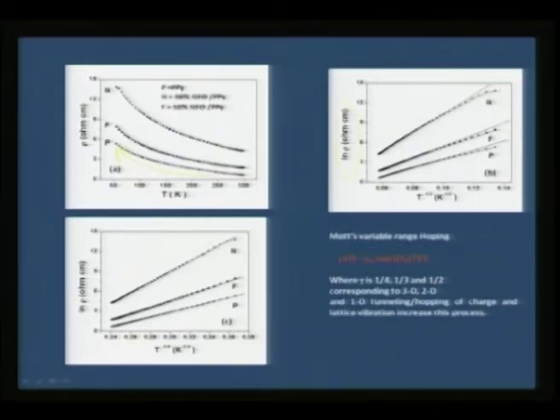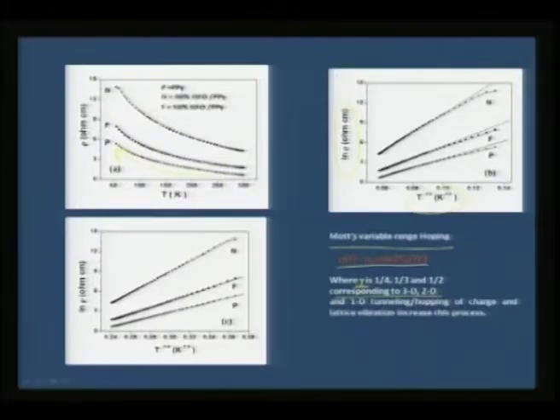Therefore, if you plot log rho versus T to the power minus half, this is typically a model related to Mott's variable range hopping. If you make a plot of this, you can see that there is almost a good agreement over the entire range for these particles, indicating that there is a 3D variable range hopping when there is larger doping of nickel ferrite, whereas with lean doping of nickel ferrite, the gamma value, that is the parameter for variable range hopping, differs from 1/4 to half, indicating that it goes through a 1D tunneling when the loading concentration of nickel ferrite is very less.